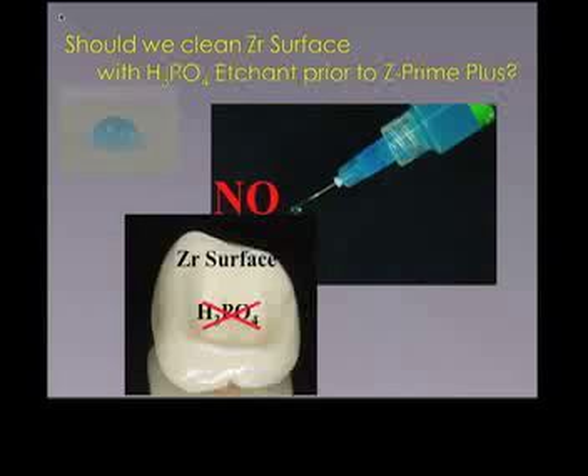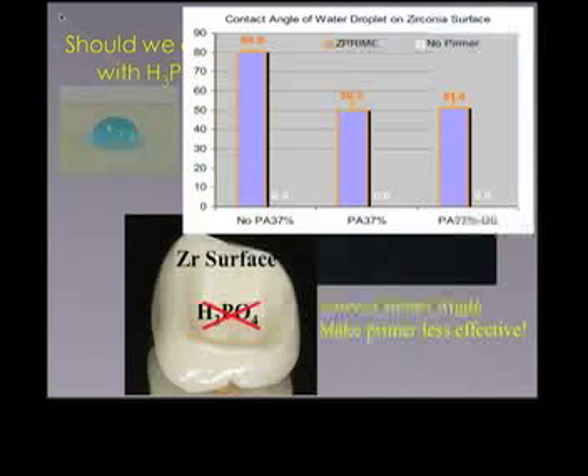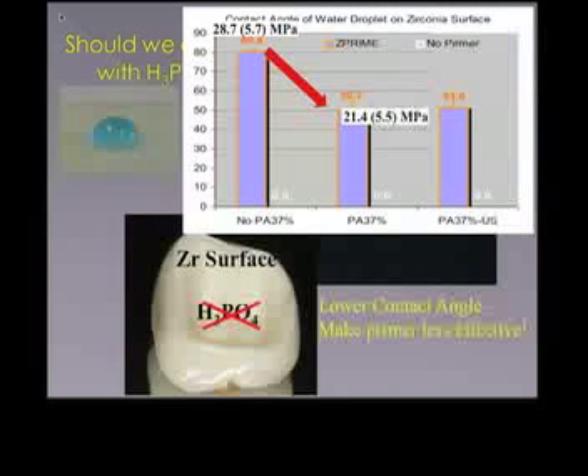Again, we're talking about a hydrophobic surface, and certainly get improved bond strength. So don't clean the zirconium surface with phosphoric acid etch when adhesively bonding zirconium crowns.